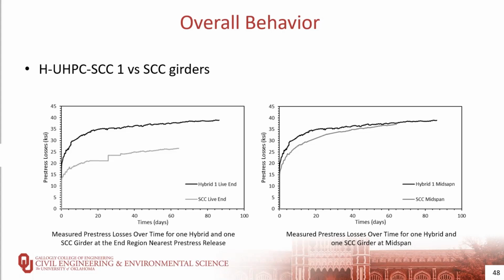As can be seen from the figure on the right, in the first 20 days after prestress release, the losses rapidly increased in the hybrid beam, corresponding to the UHPC end region high compressive stress transfer. On the other hand, at midspan, the SCC was gradually reaching the losses of the hybrid girder after approximately 60 days of prestress release, and this could be an indication of different rates of creep development in the SCC.